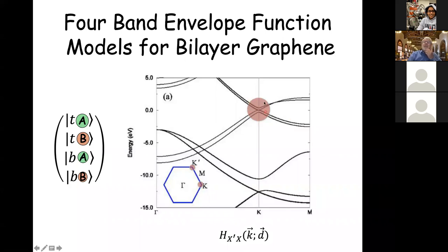Main thing I want to point out is, if we're interested in an energy range of a volt or so, all of the states are close together in momentum space, as I've been emphasizing. And we can see also here that the two Dirac cones of the two layers in this case are deformed by the interaction between the two layers in a particular way. Turns out the linear band crossing and two of the four states are pushed away from the Fermi level by around a third or so of an electron volt. And so this is because of interactions between the two layers.